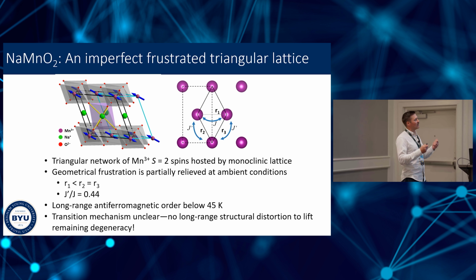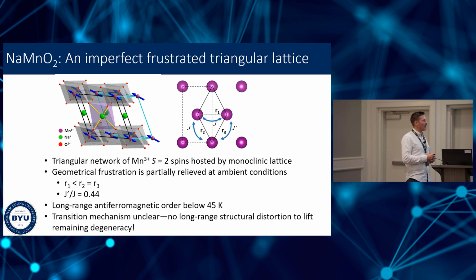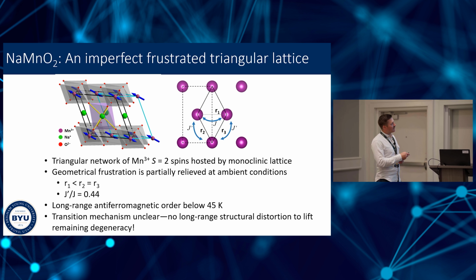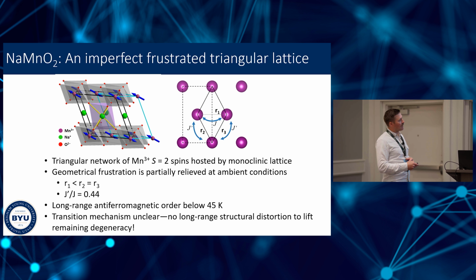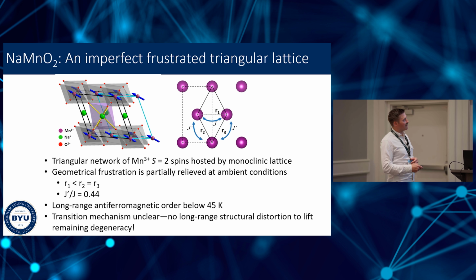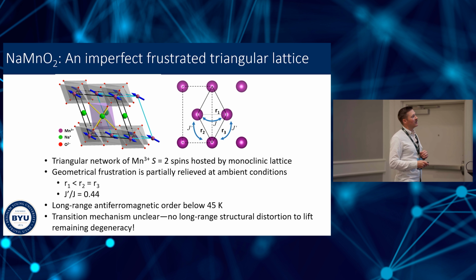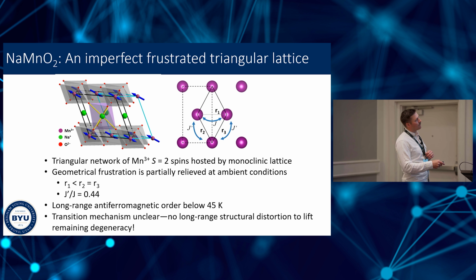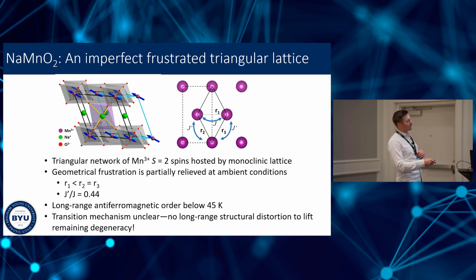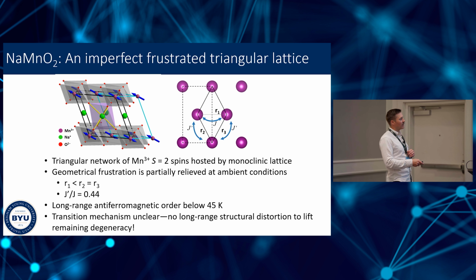Okay, so that's frustration, the essence of geometrical frustration. This material, sodium manganese oxide, has sheets of triangular lattices of manganese atoms, but they're not perfect equilateral triangles. One of the bonds is shorter than the other two, so it's an isosceles triangle. So R1 is shorter than R2, which is equal to R3. All right, we have these manganese 3 plus spins on each site.